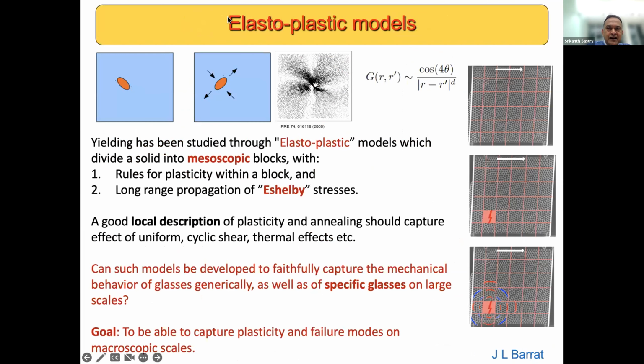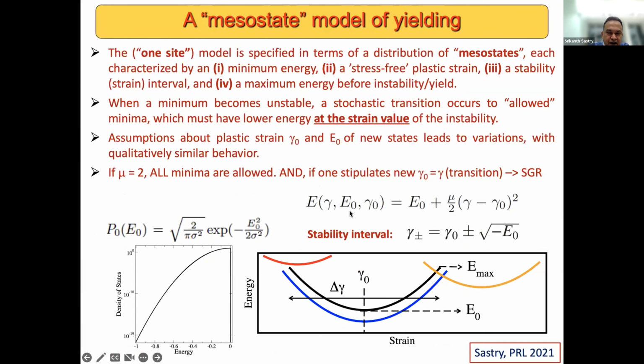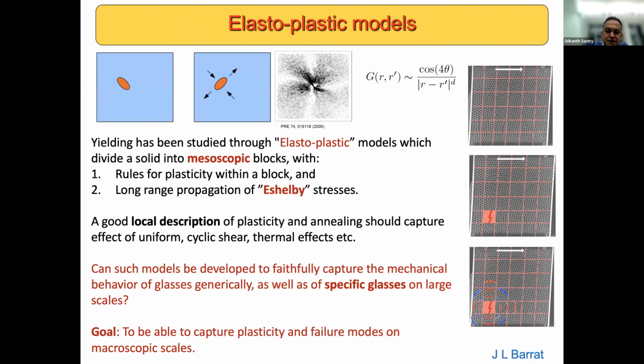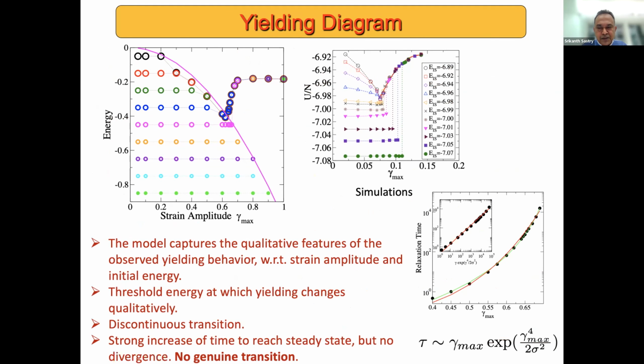And it's remarkable because, when I talked about making these elastoplastic models, I talked about mesoscopic blocks, and what I'm giving you here is a description of one of those blocks. I didn't really talk yet about interactions between the different blocks. So what I have is a one-site model, but this one-site model already captures a lot of the features that one sees in computer simulations of glasses, including the fact that if one is looking below the yielding transition, the number of cycles it takes to reach the final energies or the final state is a very sharply increasing function of the strain amplitude, but it never diverges. There is no genuine transition in that sense.